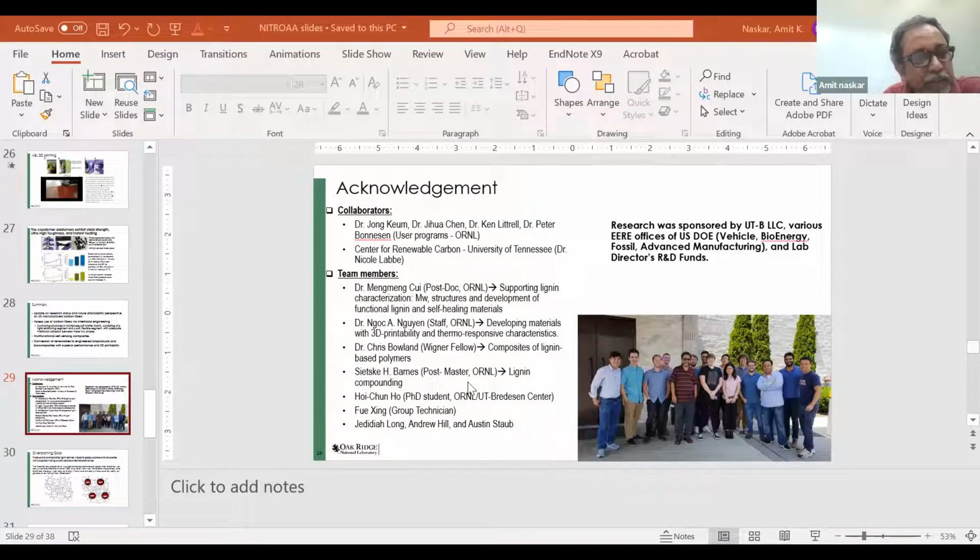Well, embodied energy, we did. This is a topic I don't do active research on, but certainly embodied energy in carbon fiber production would be high. But fortunately, carbon fiber density is very low, 1.8 gram per cc versus steel, which is probably 7.5 gram per cc. So per unit mass, if you normalize it, it can be significantly low, but volumetrically, it is still high. So I will need to dig into that data, what other folks are doing, those who are doing energy balance and other analysis, then I'll be able to comment on that. Nonetheless, the specific modulus or specific strength, performance-wise, those are significantly favorable.